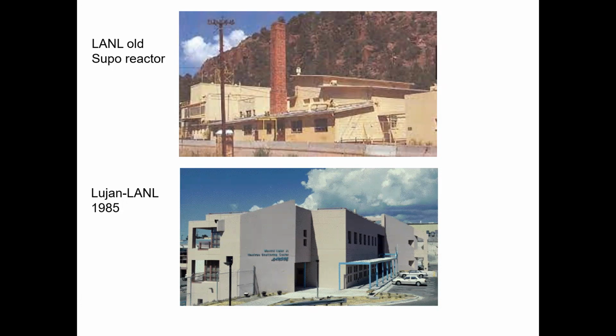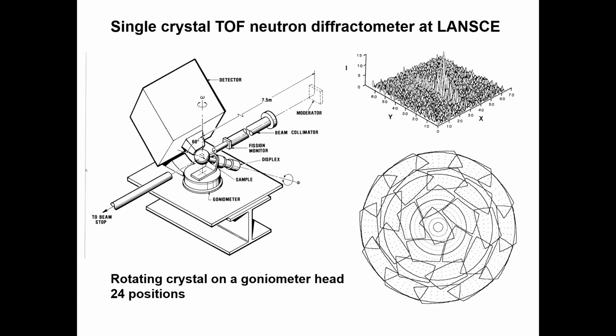But about the same time, also the Lujan Center at LANL got finished in 1985, and that's where we started experiments on the single crystal diffractometer at LANSCE, where you have a 2D intensity collection, and at the same time you use time of flight neutrons. So at each point you don't just measure a point intensity, but you measure a whole spectrum from which you can derive the orientation of the crystals.